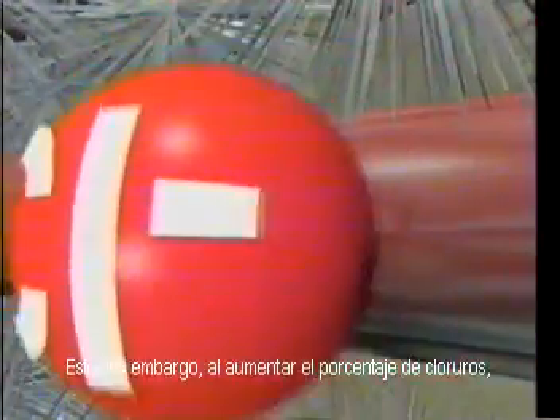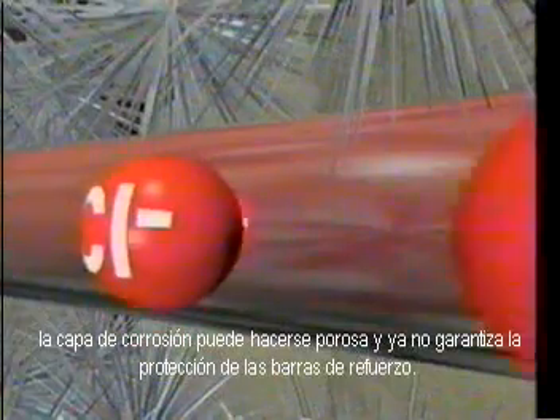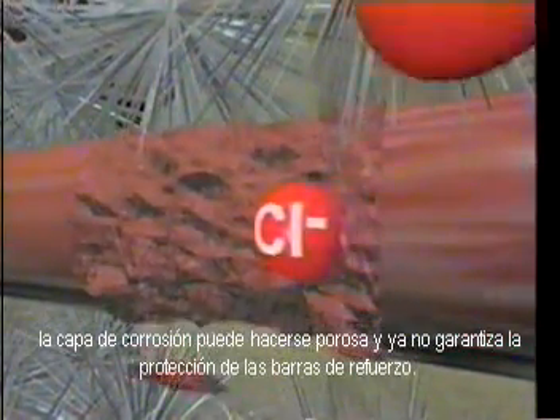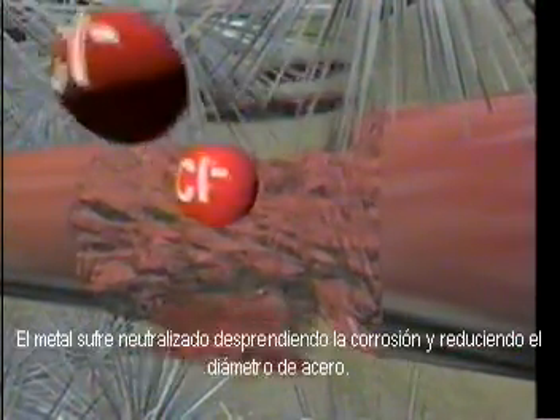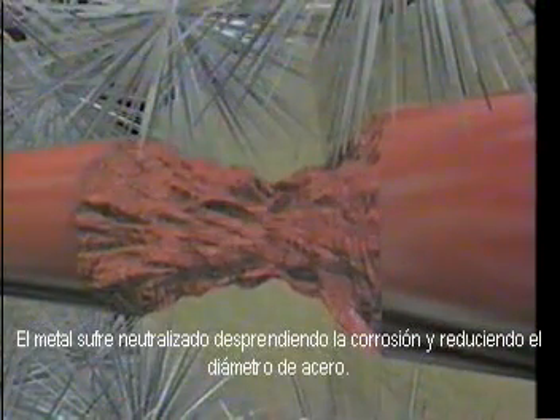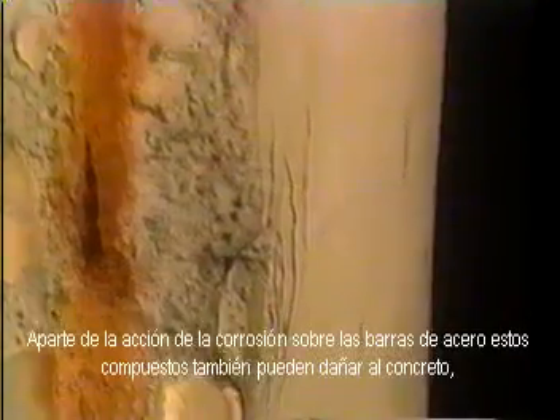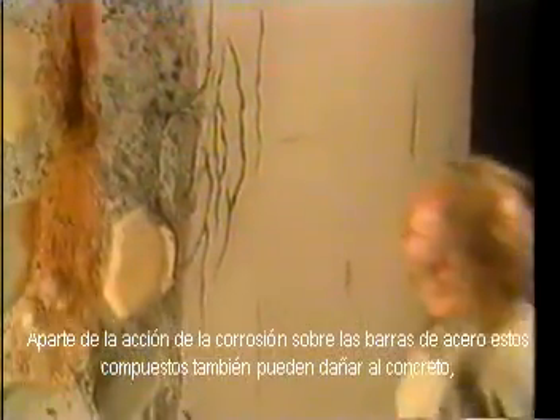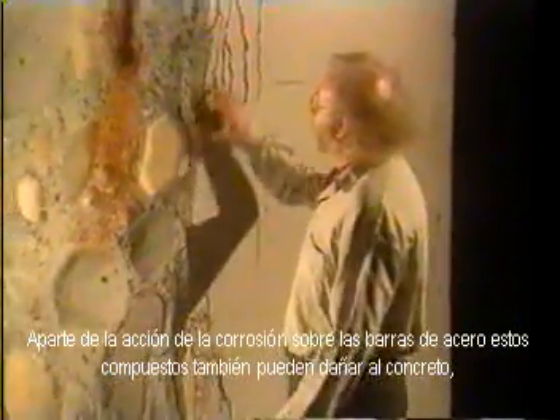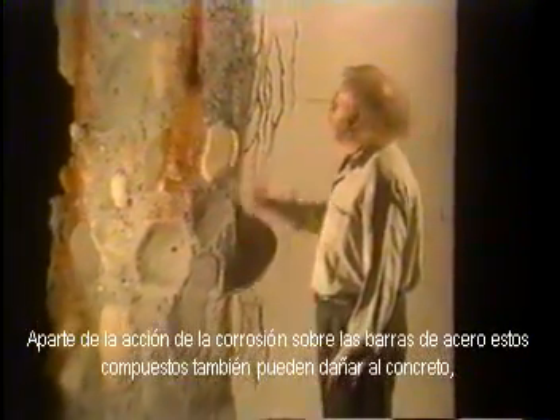If, however, the percentage of chlorides increases, the rust layer becomes porous and no longer guarantees any protection to the steel reinforcing bars. The metal undergoes localized pitting corrosion, which dangerously reduces its diameter. Apart from the corrosive action on the steel rebars, these salts can also damage the concrete.